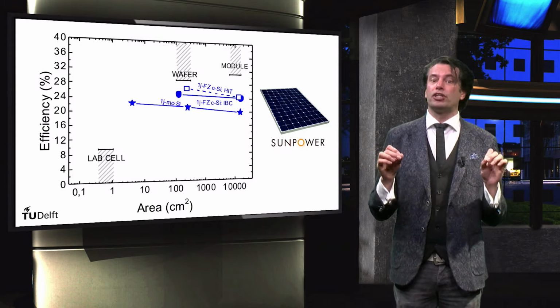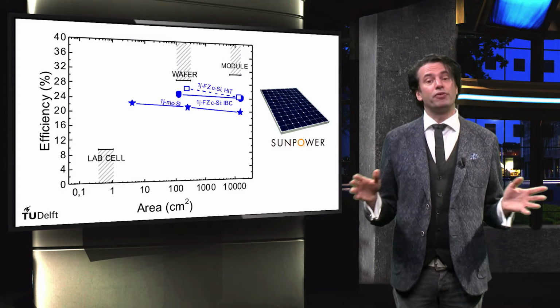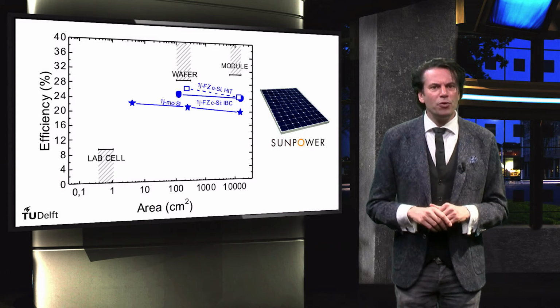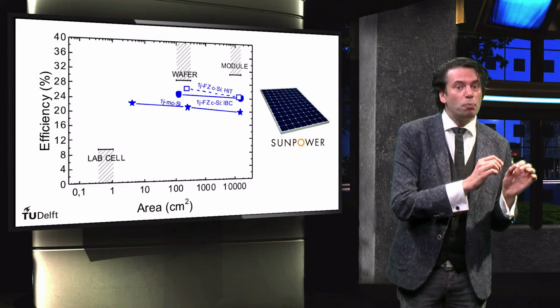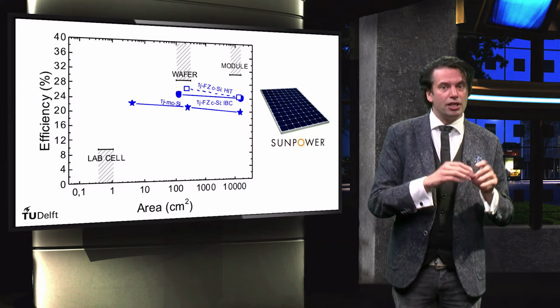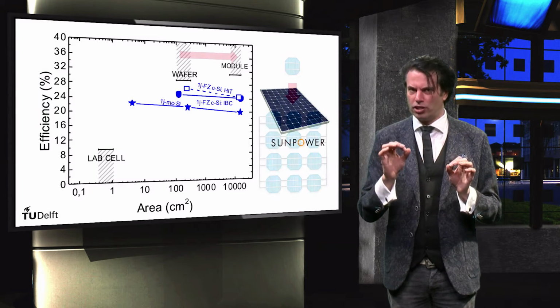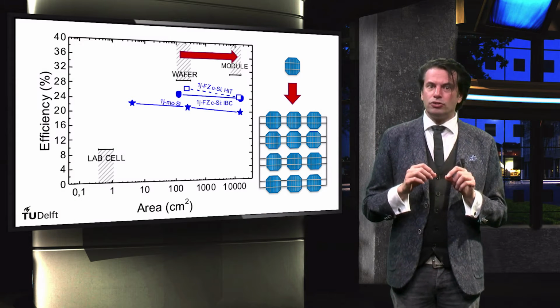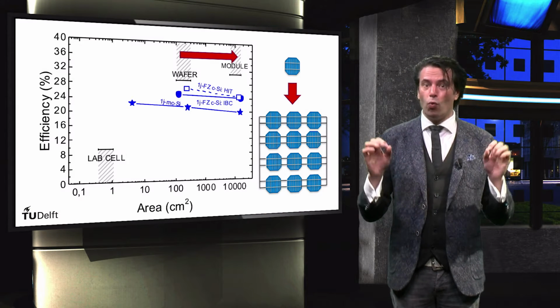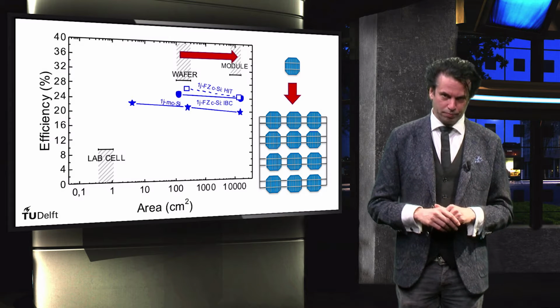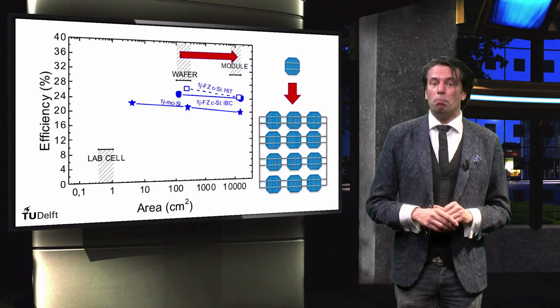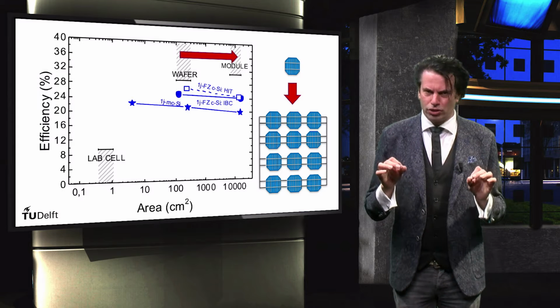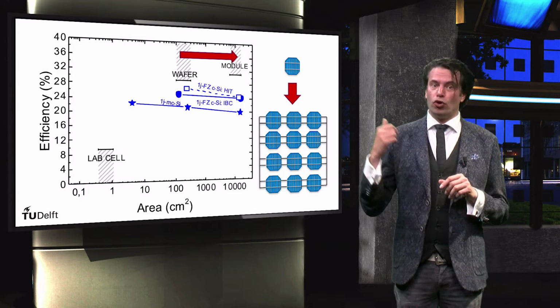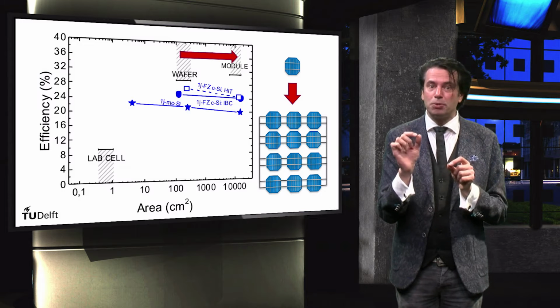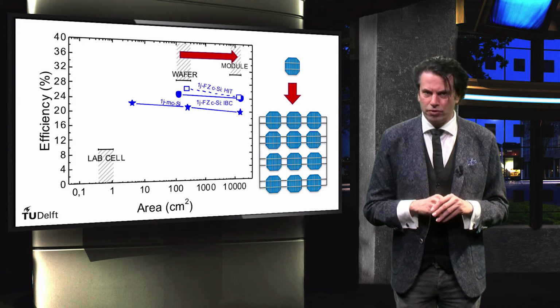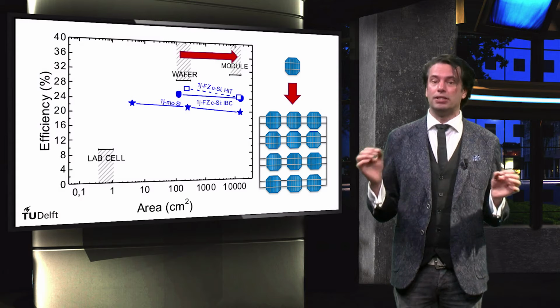Let's consider the first and the most dominant PV technology, crystalline silicon. The multi-crystalline silicon efficiencies go from 22.3% for 4 square centimeters down to 21.3% for a 6-inch wafer size solar cell, down to 19.9% for 1.5 square meter PV module. From wafer to module, 1.4% is lost. The losses are a result of lower coverage of the active area due to gaps between the solar cells and electrical resistive losses due to the interconnection between the cells.